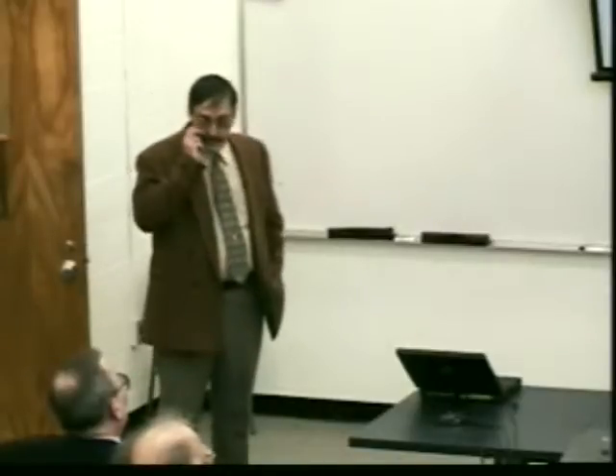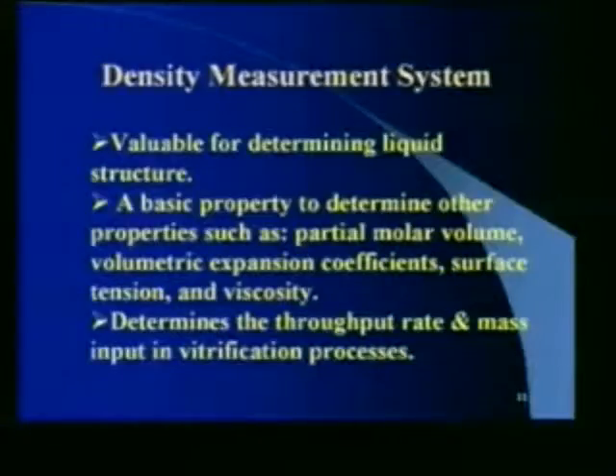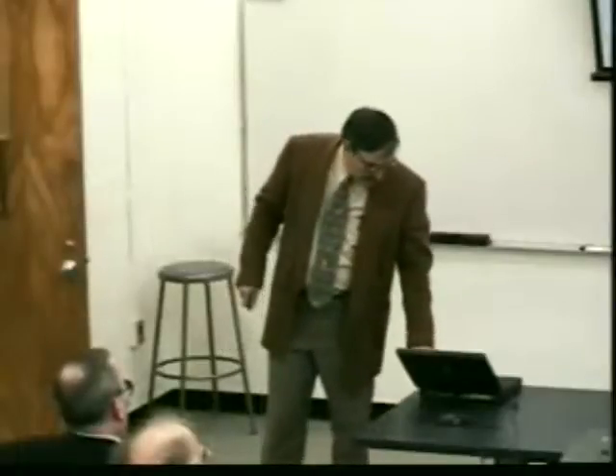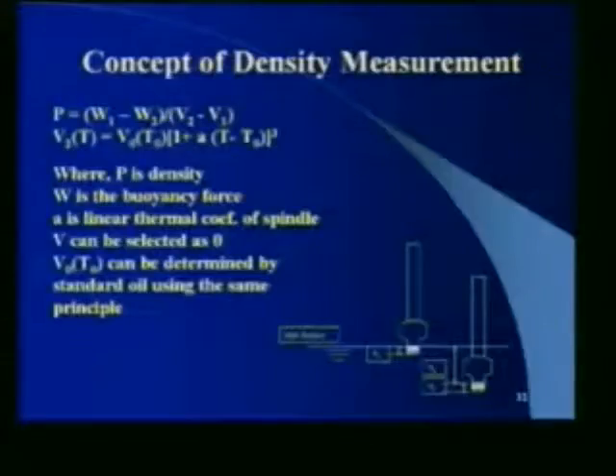The next parameter that's important to measure is density. It gives us something about the liquid structure, but also is important to basic properties such as partial molar volume, volumetric expansion, surface tension, and kinematic viscosity, and it really has an effect on throughput rate and mass input and vitrification. And so a method to be able to measure densities is also very important. And we use this kind of modified spindle method where you put the spindle in a certain level and measure the weight. You put it in a little bit all the way through and you measure the weight, and then you subtract the two.